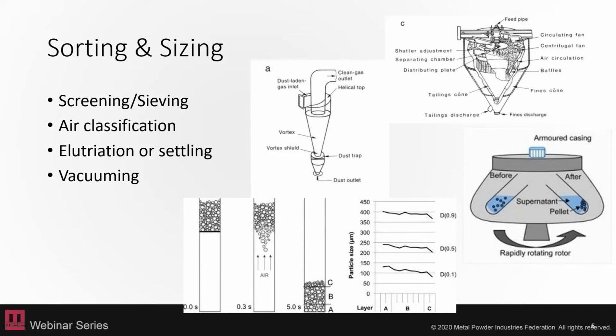You can also use elutriation or settling of the powders, and that's shown down in the bottom center, where by moving air through the powder bed, you can size classify the larger ones to the bottom, and the fines will settle toward the top as you loft the powders there. And then even just vacuuming your powders can help you sort and size them.